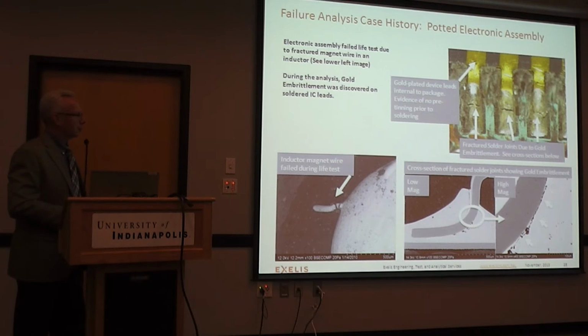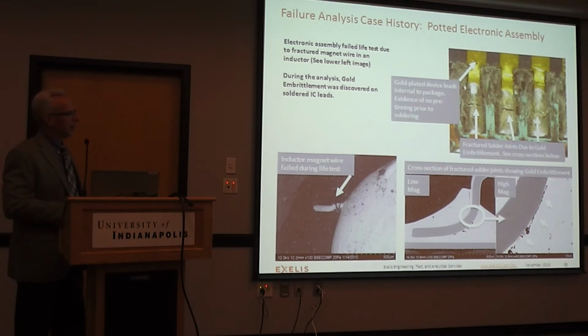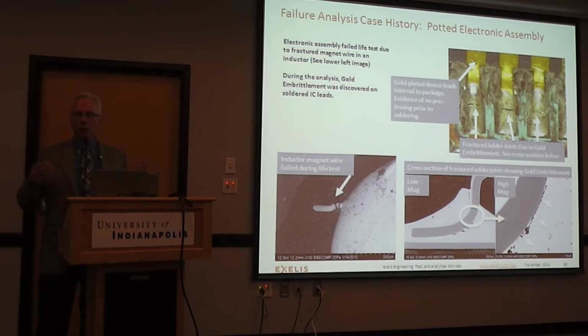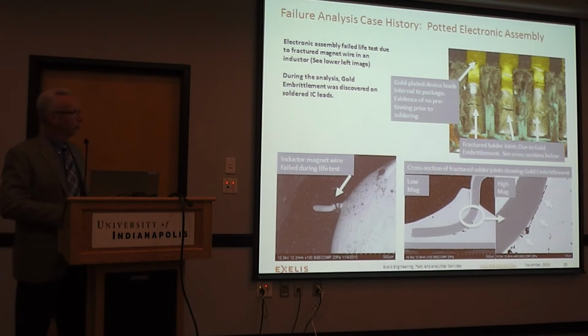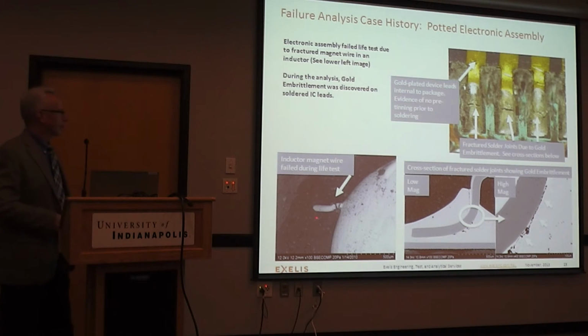Okay, so we were able to determine the root cause of failure not just by this image. This was a clue. This was a visual cue that, oops, it looks like somebody forgot to do a very important step. So in a high reliability program, it is standard to do a pre-tin on a gold-plated device to avoid gold embrittlement. And when we did the cross-sectioning depicted down here, we confirmed that gold embrittlement was at play.